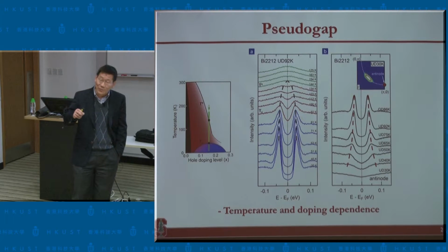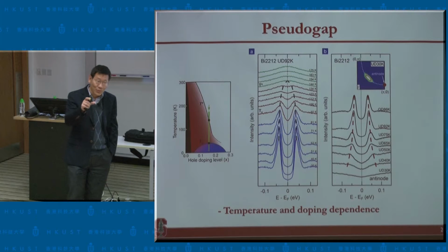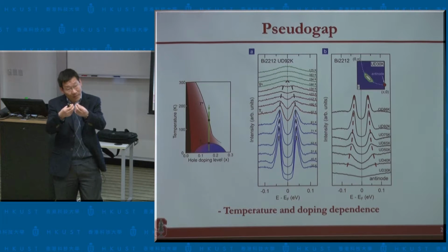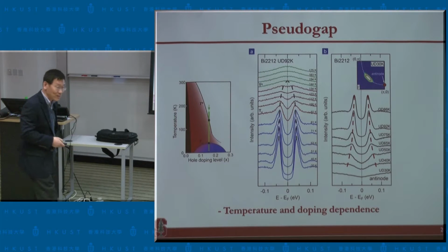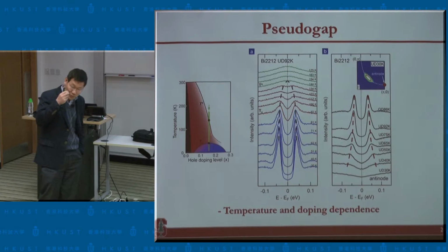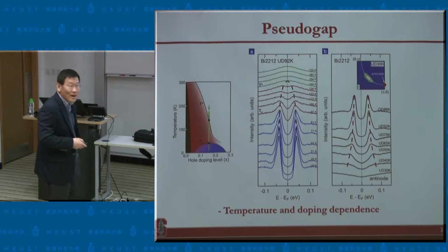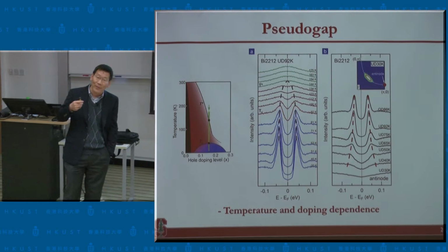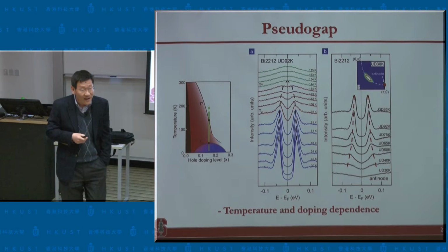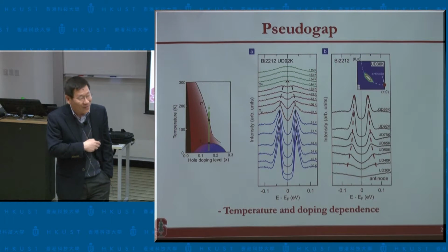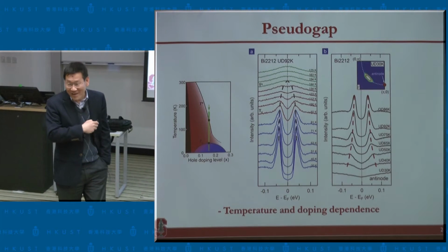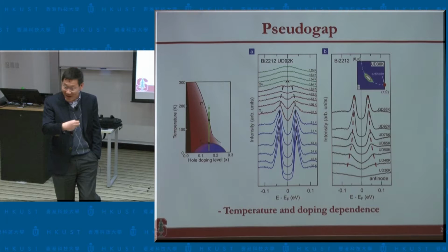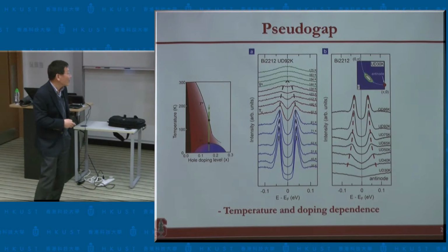The reason is that in conventional superconductors, the energy gap has a special meaning for superconductivity because it's the energy it takes to put two electrons together in a Cooper pair, or the energy it takes to break it. So it's special, but that happens only in the superconducting state. The fact is, this is in a normal state. I remember very vividly, we were the first to discover the D-wave gap, and we got a lot of positive feedback on that. And then we found this. I remember I told Dan in one of the evening shifts we took together, I said, Dan, it may well be that everything we have done is wrong. Because to have a gap in the normal state today is very natural. Back then, it was such a strange phenomenon.